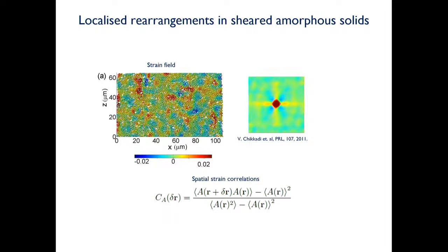That's how the disordered system is going to deform when you apply stresses on it. In the case of crystals, you have dislocations that travel from one point to another, but in this case, the dislocations are these shear transformations, okay. They are the plasticity carriers. That's how plastic deformation arises in these systems. Now the second question is, what we have done so far is we have characterized how deformation occurs in these systems, and what the characteristics of these plasticity carriers are.